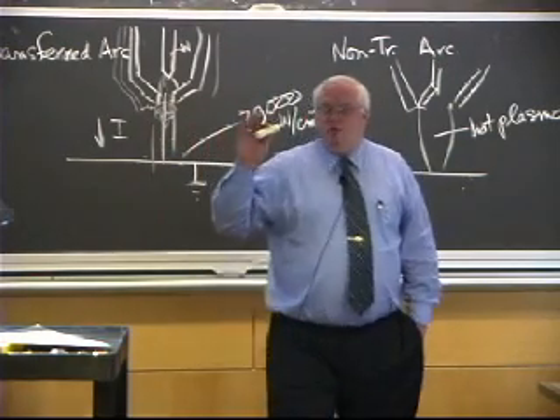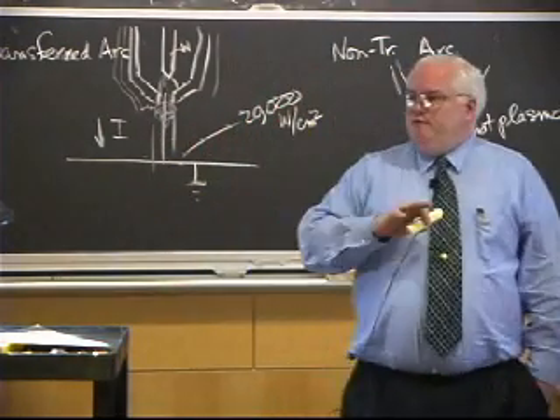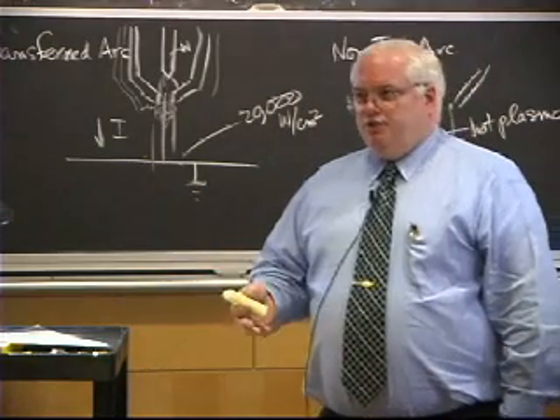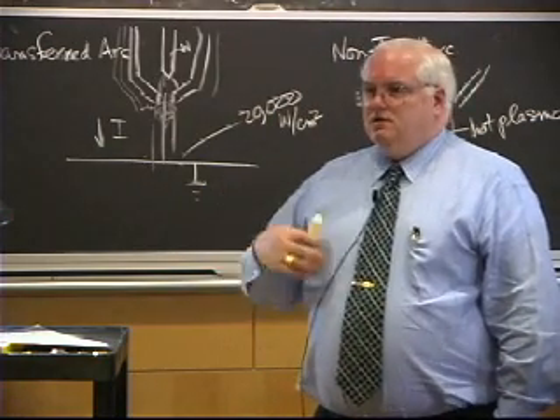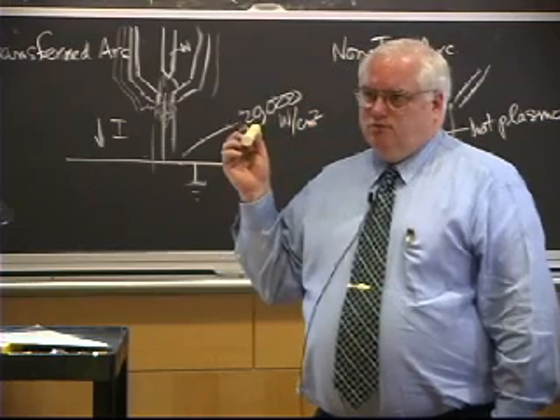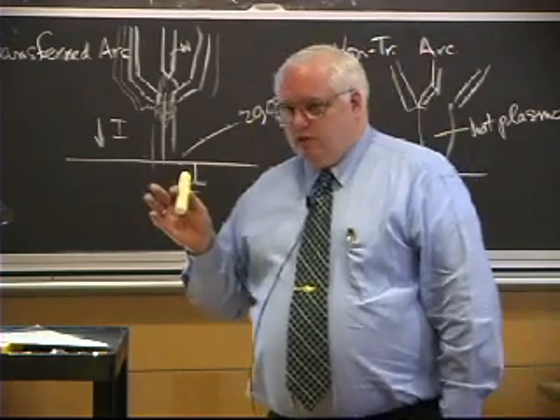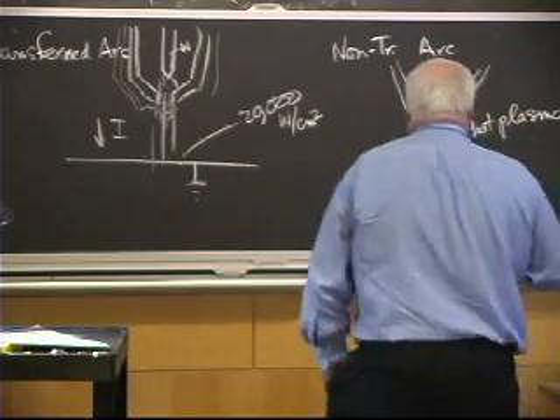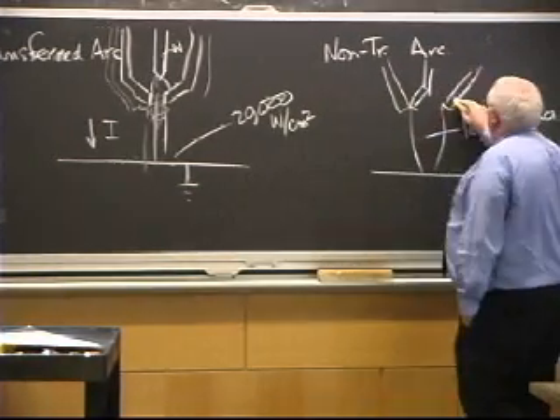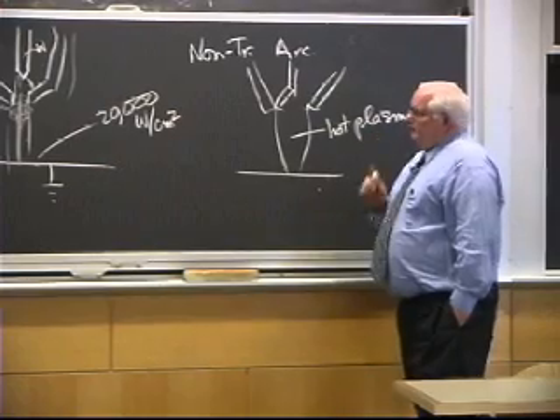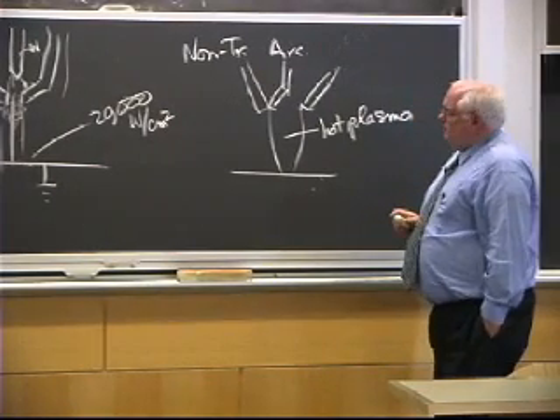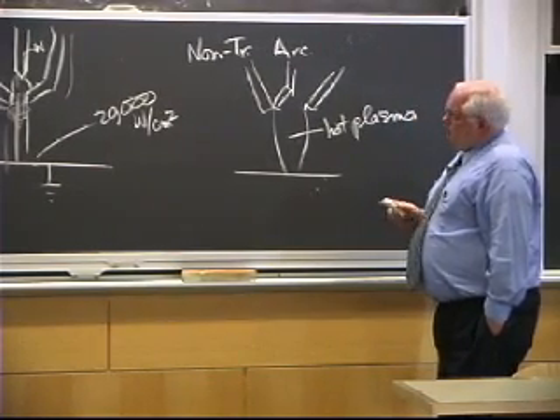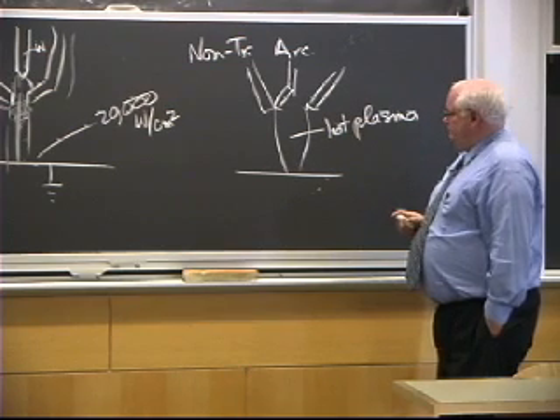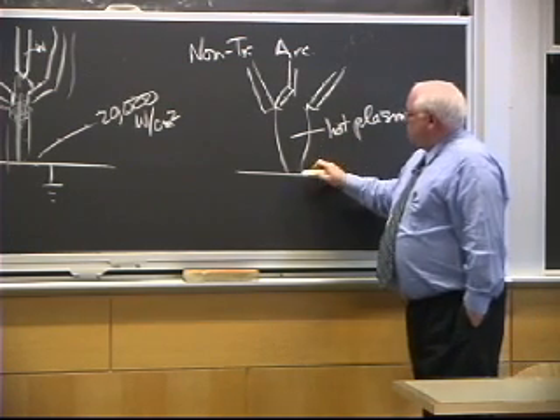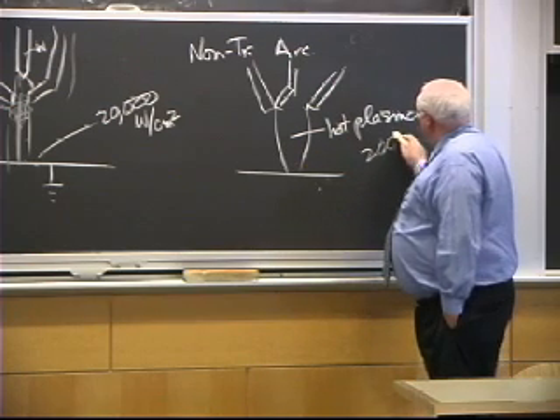So it turns out I like plasma arc for welding aluminum. I like plasma arc for welding copper. They have very high thermal conductivities. I can get much more efficient welding. The space shuttle main tank is welded by a special type of plasma arc. Okay? NASA can afford anything. Well, anyway, they weld the space shuttle main tank, which is aluminum, of course, by what they call variable polarity plasma arc. In non-transferred arc, you only get about 2,000 watts per square centimeter.